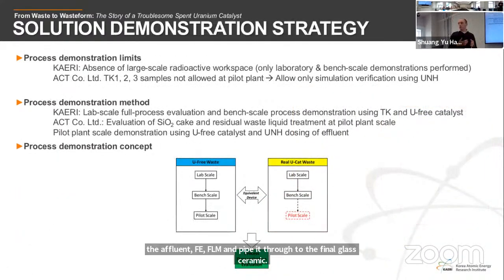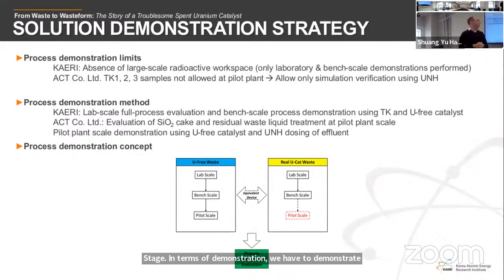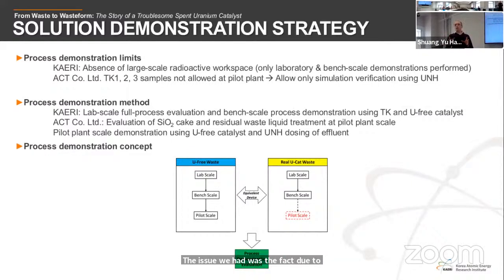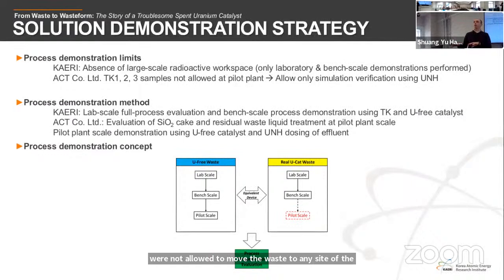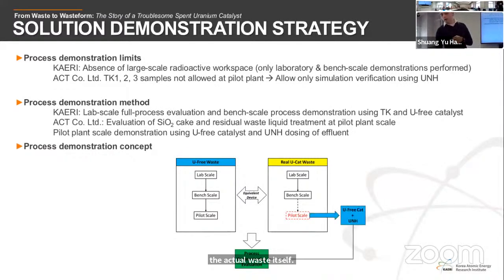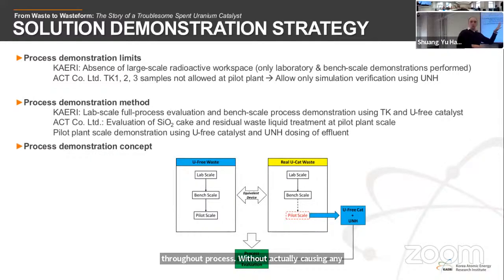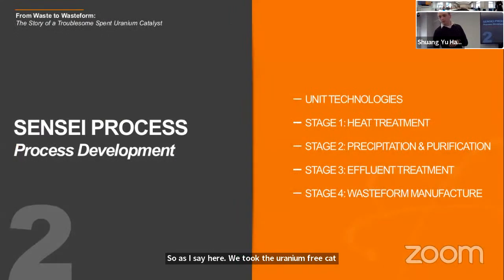In terms of demonstration, we had to demonstrate that we could use this process on the large scale. The issue we had was that, due to regulations, they were not allowed to move the waste to any site other than KAERI. But at KAERI, we didn't have sufficient space to run the pilot scale. So what this meant was that we did all of the testing with the real waste at KAERI for the lab scale and bench scale. We couldn't do the pilot scale. Then we simultaneously ran non-uranium containing waste catalyst through the lab scale, bench scale, and pilot scale testing. At the pilot scale, we then introduced uranium into that process, but not the actual waste itself. So it allowed us to follow the path of the uranium throughout the process without causing any issues. We took the uranium-free catalyst, combined it with UNH, and we were allowed to process it.